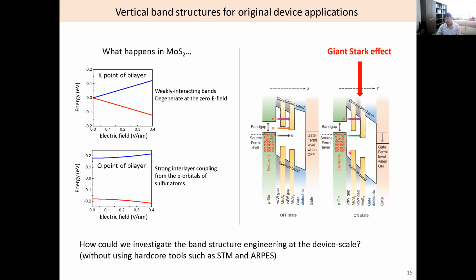And again, if you learn quantum physics, quantum mechanics, this is similar to the Stark effect. In the beginning of quantum physics, for hydrogen atoms, many electronic states are degenerate, and then by subtle electronic wave function change, we have this broken degeneracy. So this is similar to the situation. In the bilayer case, in vertical electronic structure, we apply a voltage like 1 volt through 1 nanometer. So we apply a huge electric field, and we have such momentum dependent things which other scientists don't consider.